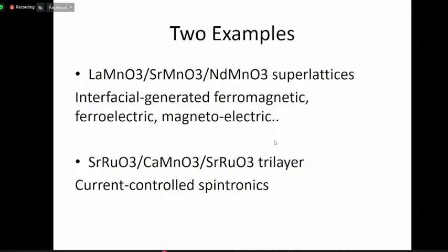Okay, today I'll show you two examples. One is a manganite using lanthanum, strontium, and neodymium, and we make a superlattice. The other one is strontium ruthenate, calcium manganese oxide, and strontium ruthenate. It's a tri-layer, using just three layers. The manganite is sandwiched by two strontium ruthenate layers.